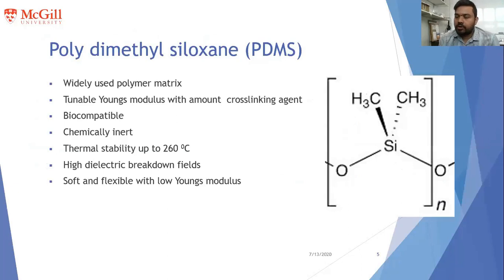Coming to the matrix, we used PDMS, which is polydimethylsiloxane, another widely used polymer matrix. The important feature of PDMS, which is why it is used in many different composites, is that you can control the flexibility of the film, like the Young's modulus, with the right amount of cross-linking agent you add to the PDMS base. It's also chemically inert, biocompatible, and thermally stable to high temperatures.